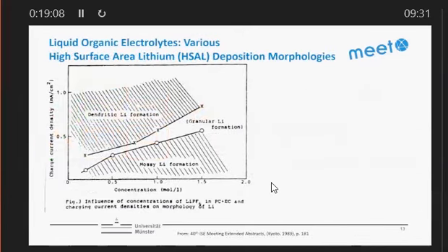Okay. What we see is that when we are looking at dendrites, it's very important what we are putting together as chemistry in liquid electrolytes. This is well known: additives, which solvents, and also which electrochemical regime we are applying. This is a picture from 1989, which already shows that this has been done before on lithium metal. We see here three different morphologies of lithium metal: mossy lithium, dendritic lithium, and in between the granular lithium. The granular lithium is the more compact one, so this is the one which is actually desired in liquid electrolytes.